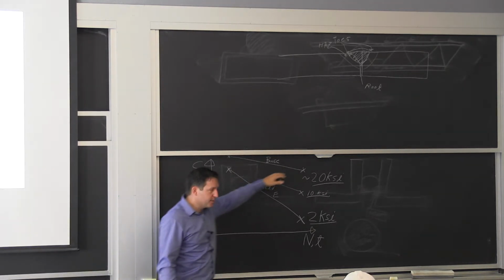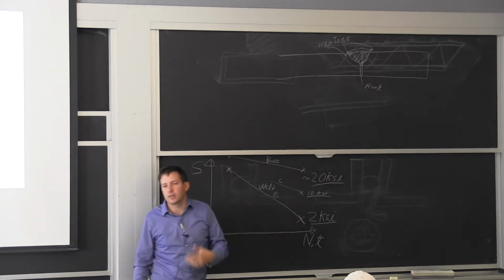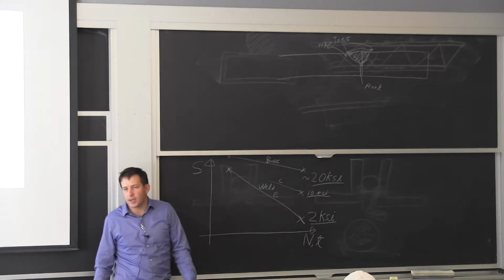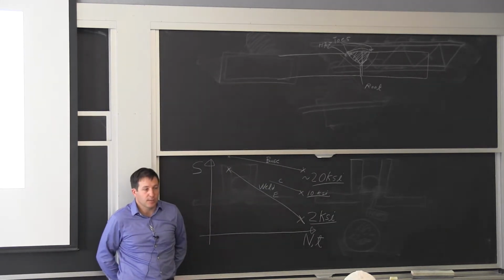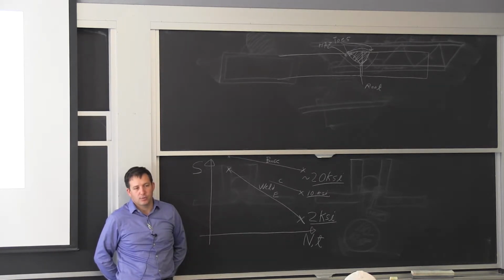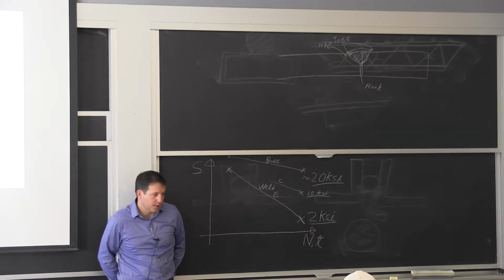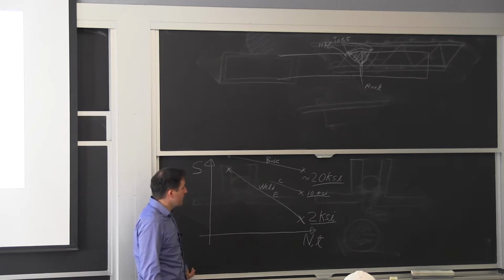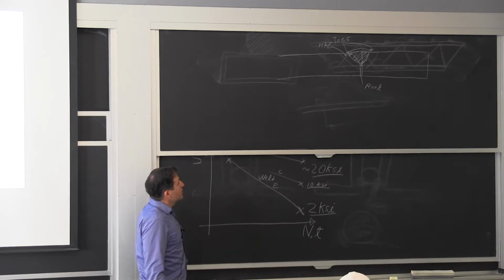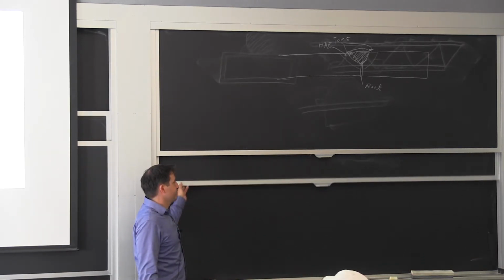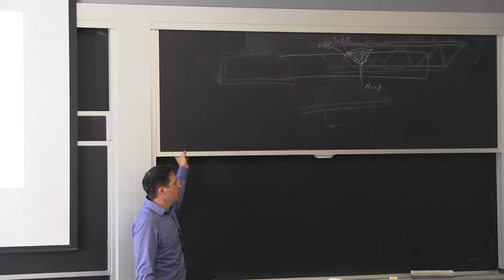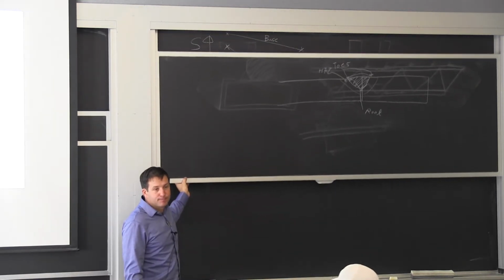And that's why I'm starting to initiate cracks in conditions where normally I can see there's really not much demand on my structure. Locally there is, and that's how you start the cracks. When the cracks have started, they're very hard to stop unless you stop the loading.